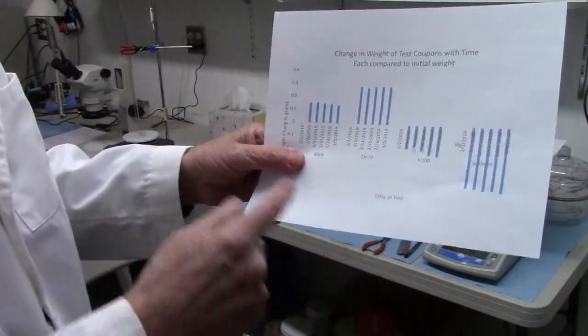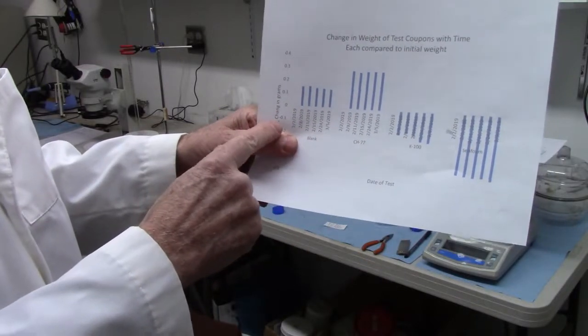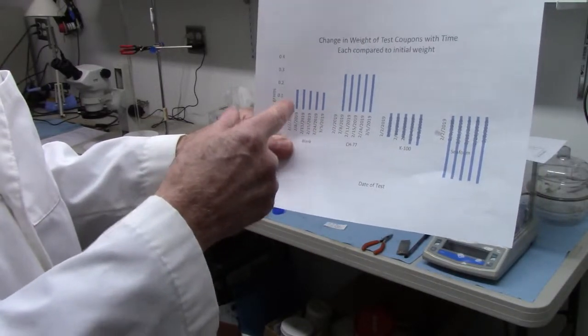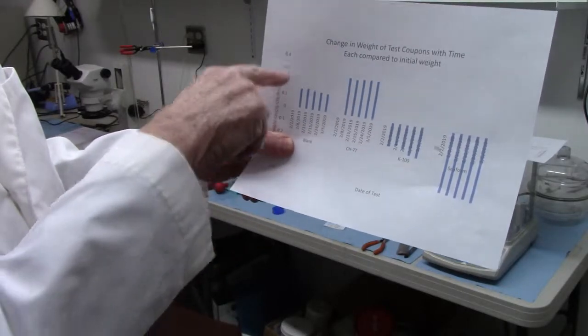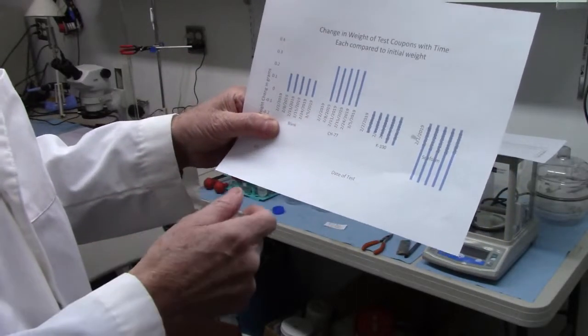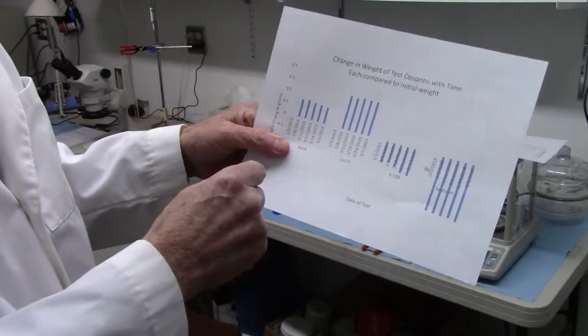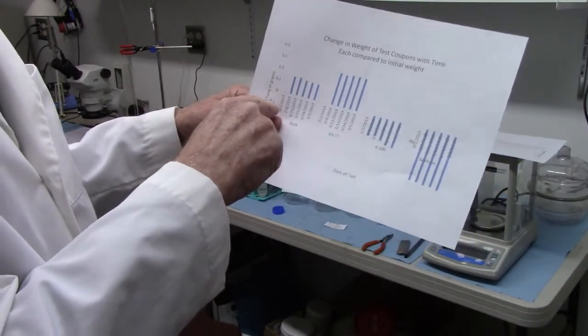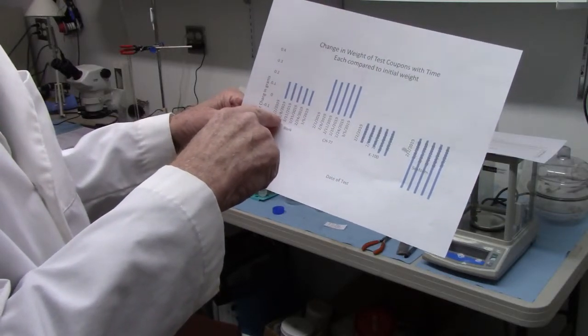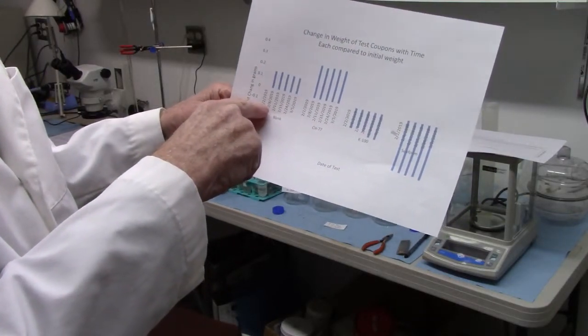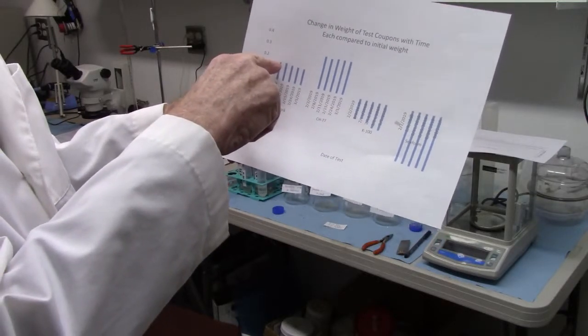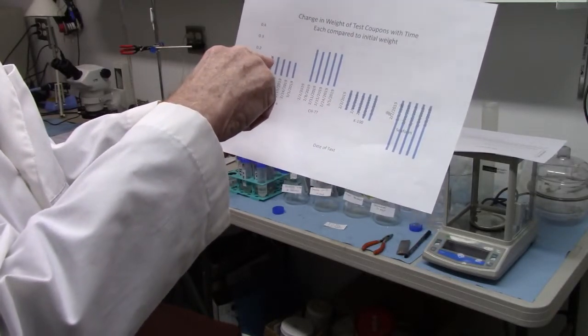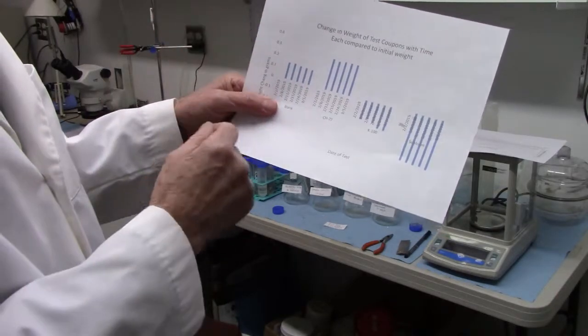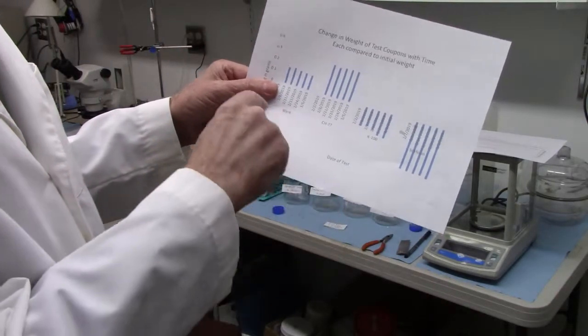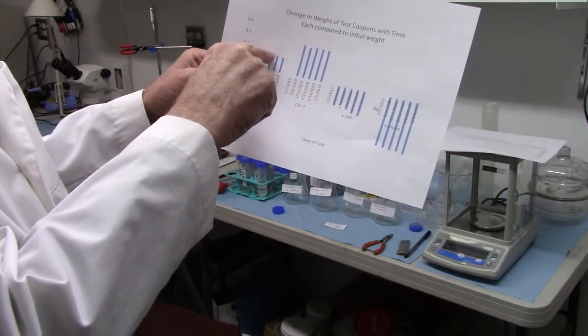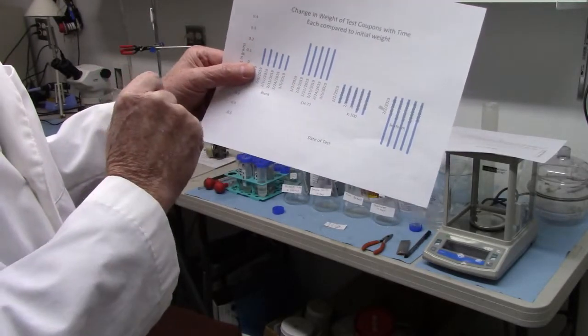This is with the plain water. This is the blank, this is day 1. These are days here, and this is the weight change from when it was first put in. You can see on the first test date, 6 days after I started, the weight of the coupon went up by this amount, like 0.15 grams, 150 milligrams. And then it steadily deteriorated.